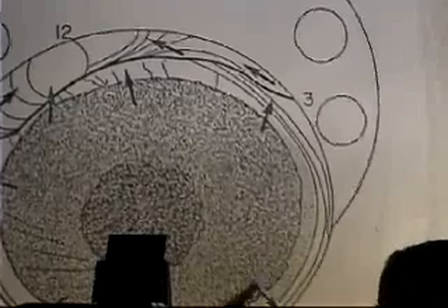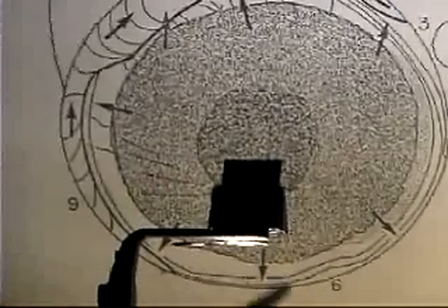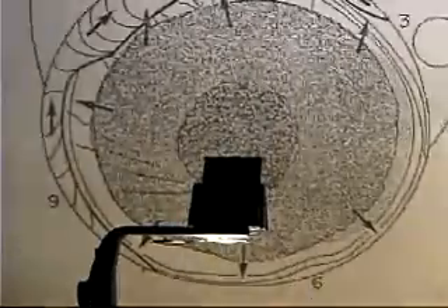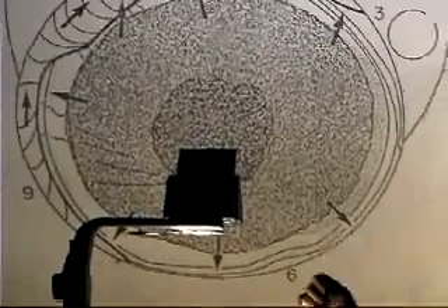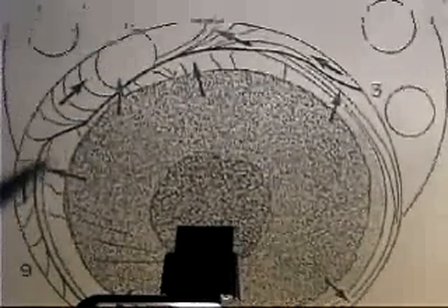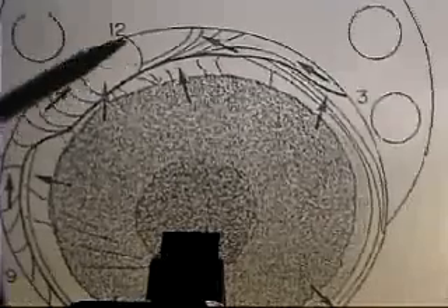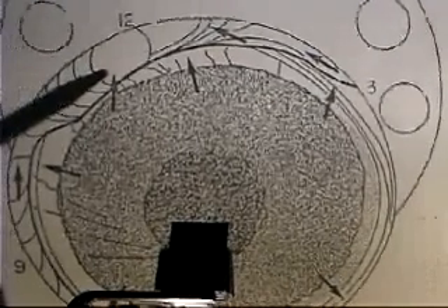The rest of this and these other lines on here, the crack grew out this way, and then fatigue cracks in operation grew this way in rotating bending. And remember I showed you the fatigue crack pattern. You can go back to that and you can prove to yourself. The final fracture was right up here. Okay, we call that 12 o'clock. And you can see all the arrows converging, and that was the final area of separation, which meant that this thing was very lightly loaded.